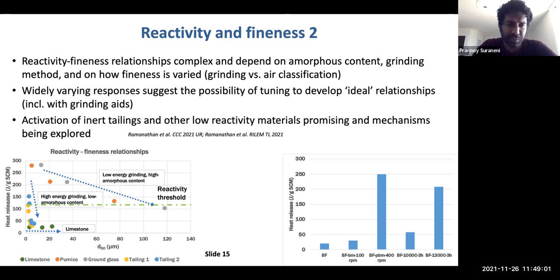Now, we've shown here that activation is possible, and we wanted to look a little bit more at activation. So what we did is we took these basalt fillers. Basalt fillers or basalt fines, at least the ones we tested, were inert. So we put them in a ball mill, which is relatively low energy, at 100 RPM for 1 hour. And you see that essentially nothing happens. The heat release goes from maybe 30 to 40.